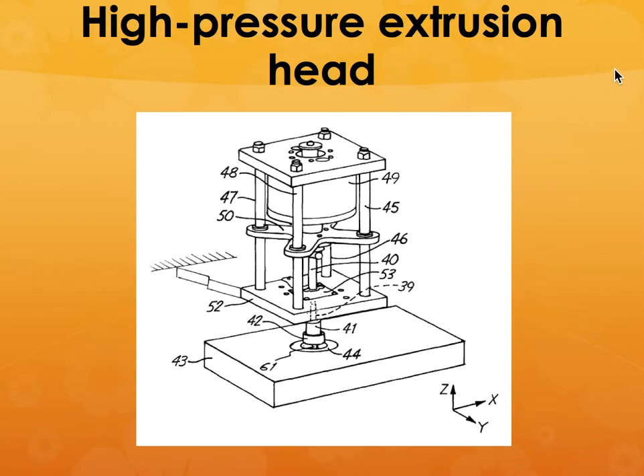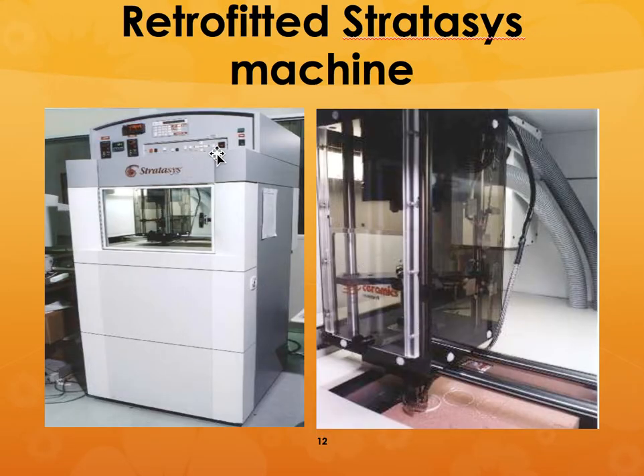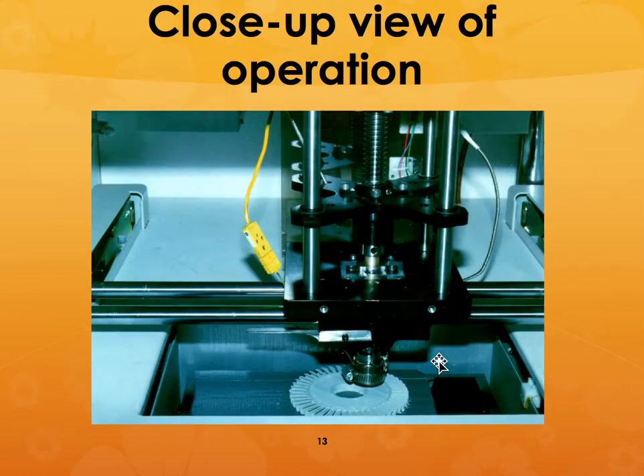So, but we did overcome a lot of problems. We came up with what is called a high pressure extrusion head that could be attached to the Stratasys type of a machine, because when you add fibers and when you take high pressure high strength polymers, you need much higher pressure to extrude out the material. So we put a high pressure extrusion head on that machine, a standard Stratasys machine, and we retrofitted that with a high pressure extrusion head. And it gave us the strength that is required to extrude out that material.